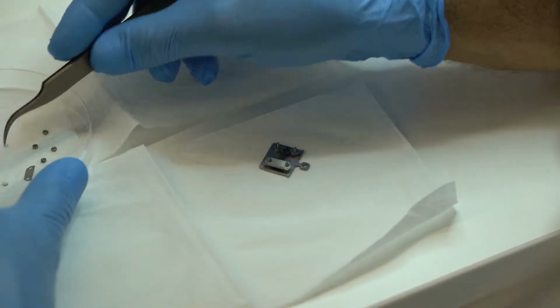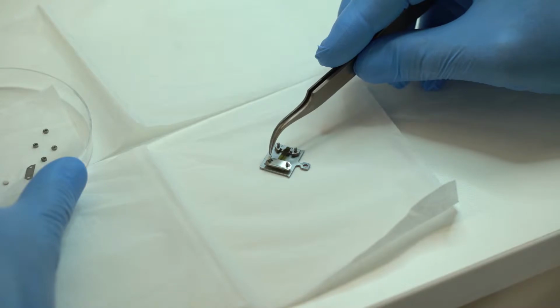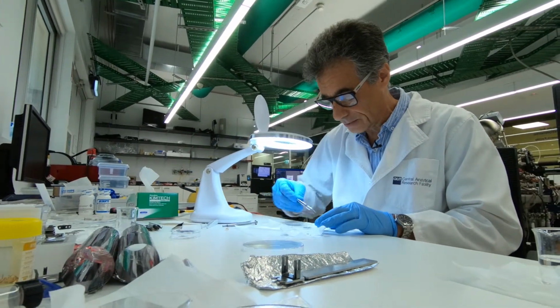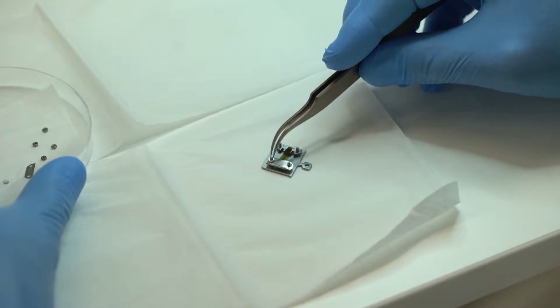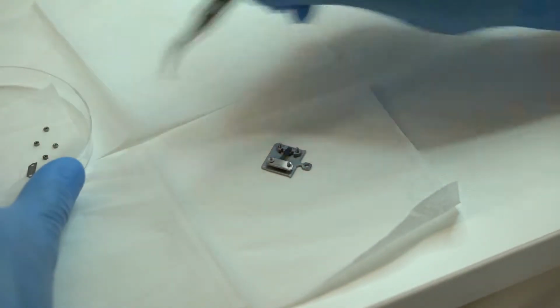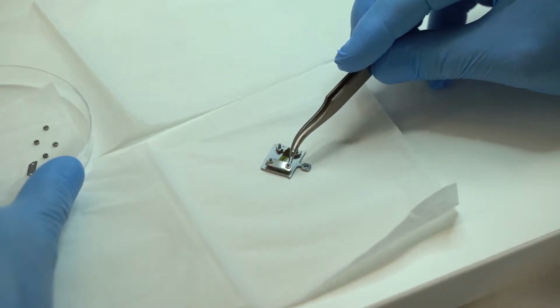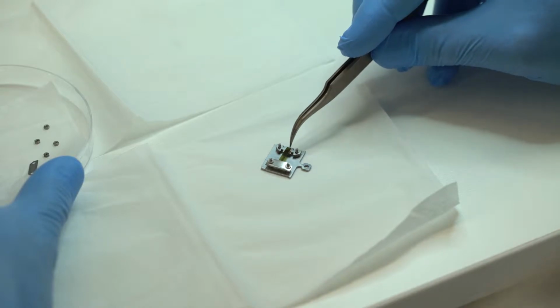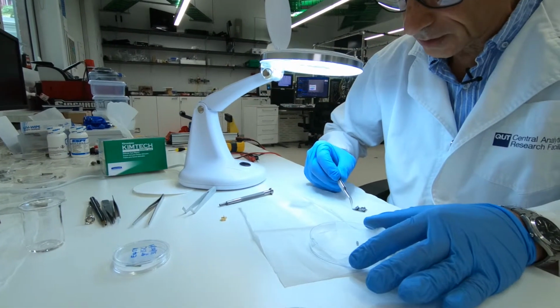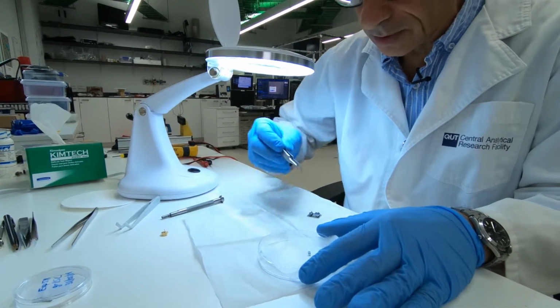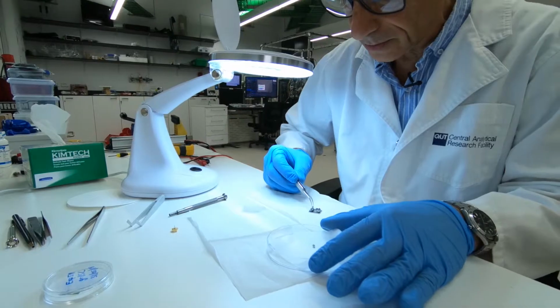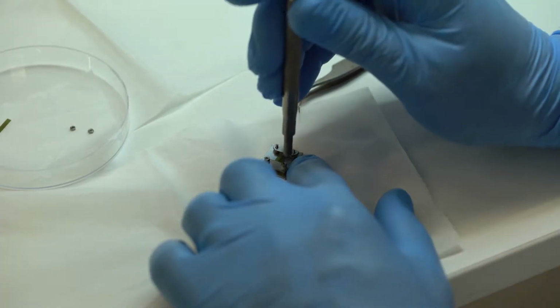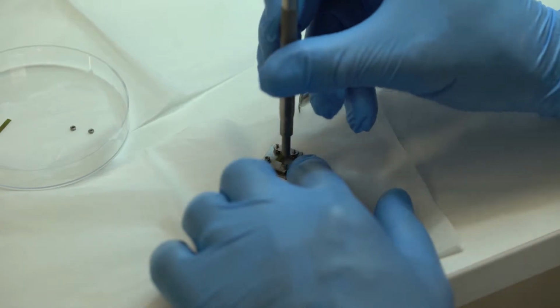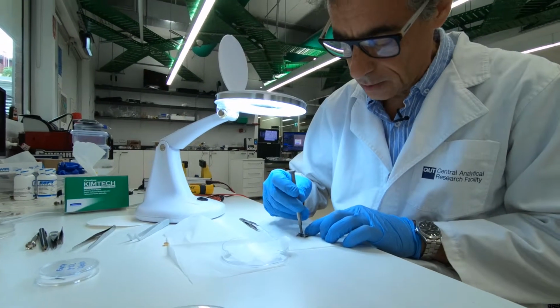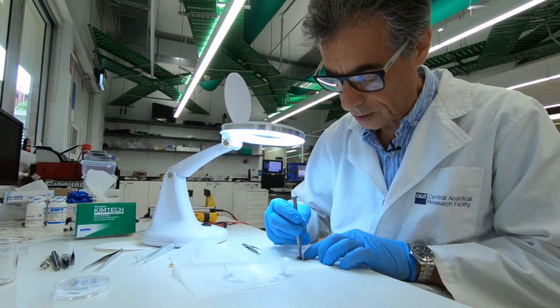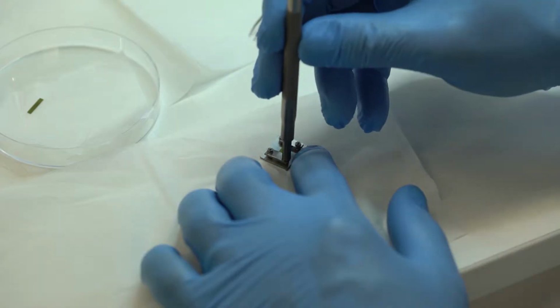The sample is going to be heated in a direct current mode. That means that the current will flow through the sample. And I need to put also these insulating rings here. And I need to screw in these nuts to get the sample secured to the sample holder. And I use this special tool in order to screw in the nuts. We just do a little bit of shaking to make sure that we secured it well.